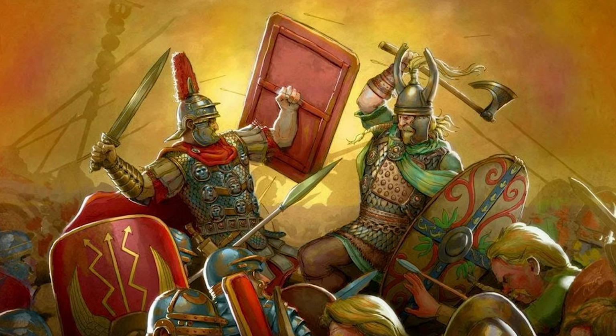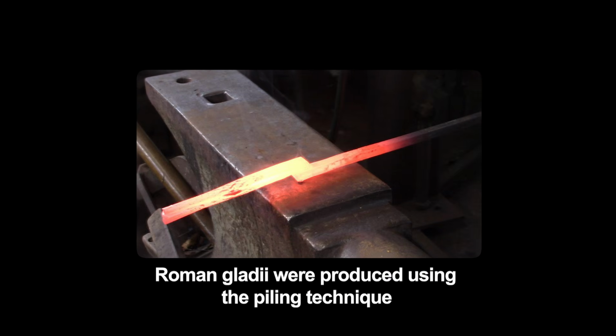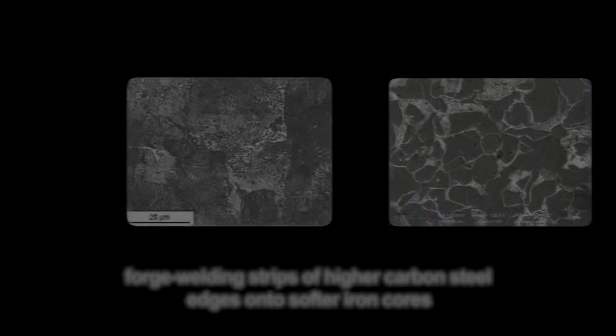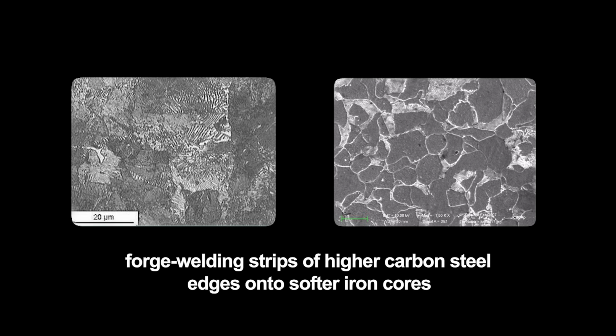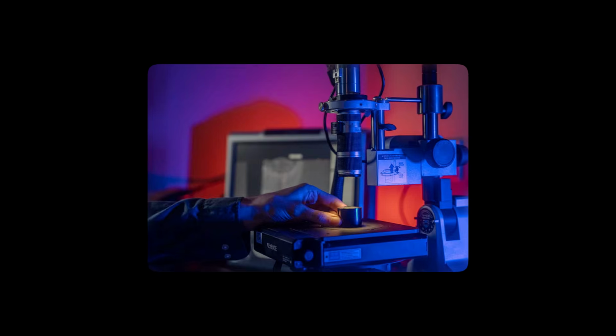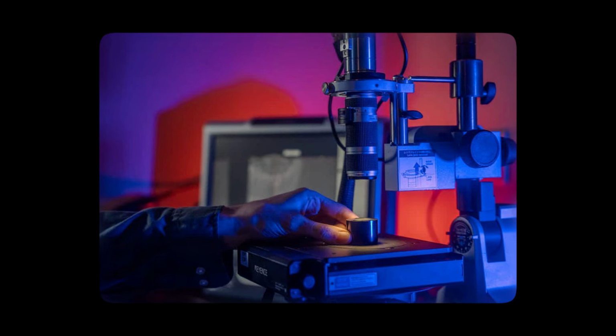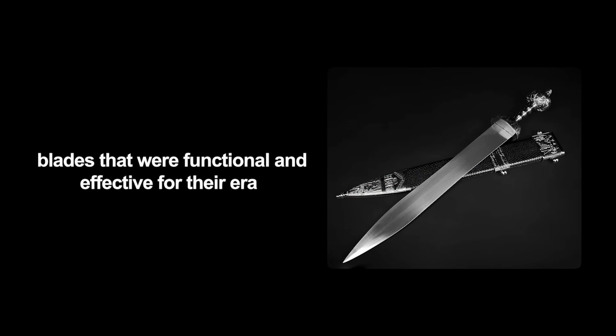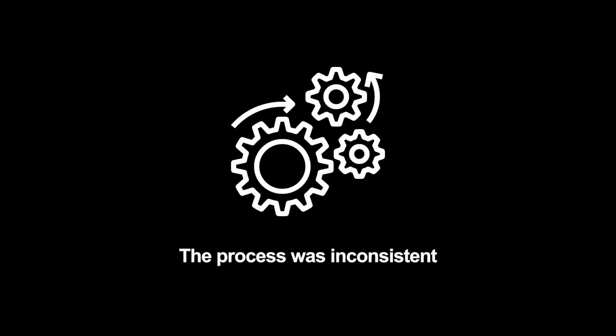The steel gap that shouldn't exist. Here's where the history becomes genuinely shocking. Roman gladii were produced using the piling technique, forge welding strips of higher carbon steel edges onto softer iron cores. This showed real metallurgical understanding and produced blades that were functional and effective for their era. But the process was inconsistent.